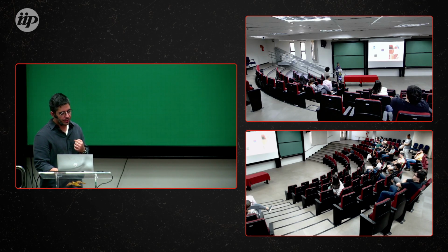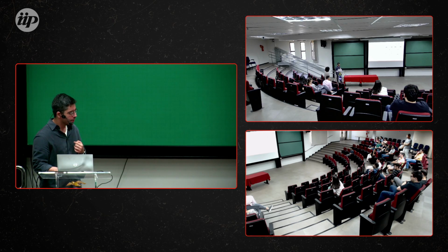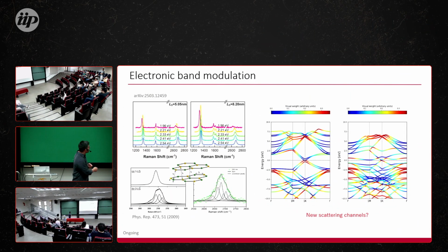So what I can tell you is, let me go back a little bit in here so I can answer your question properly. I didn't mention it, but if you pay attention, even for graphene itself, the intensity of this band kind of disappears, right? For higher concentration, the 2D band intensity disappears. This is an intervalley process where the phonon is being scattered from K to the K prime valley, and then comes back. So we have two phonons. They are in-plane TO phonons, basically, transversal optical phonons.